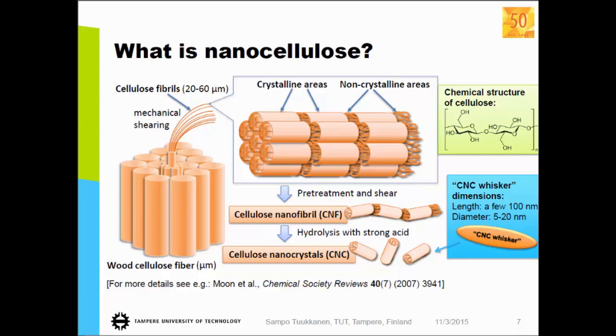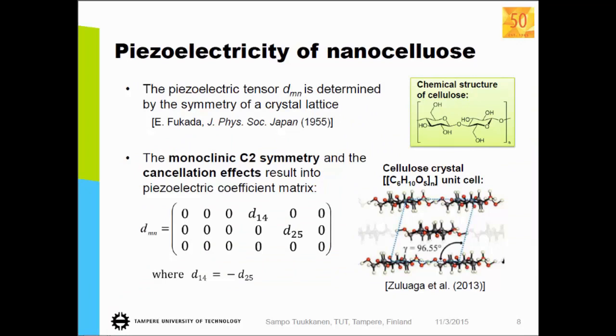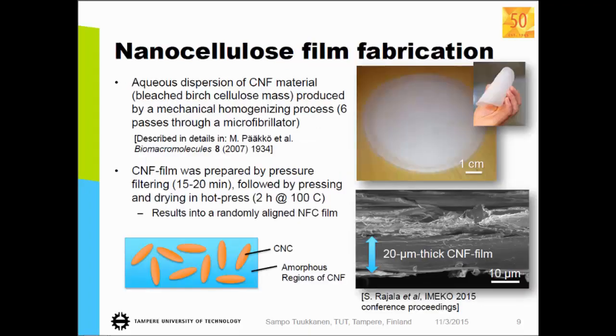And the interesting thing is that these nanocrystals have piezoelectric properties. So this was already found like 60 years ago. The crystalline structure of cellulose, like here it's one unit cell of the cellulose crystal, and then by calculations, taking into account the symmetry of the crystal and some cancellation effects, you end up with this kind of piezoelectric tensor matrix. So you have only two components which are non-zero, and these are the same magnitude but opposite sign. And this is what we have started with.